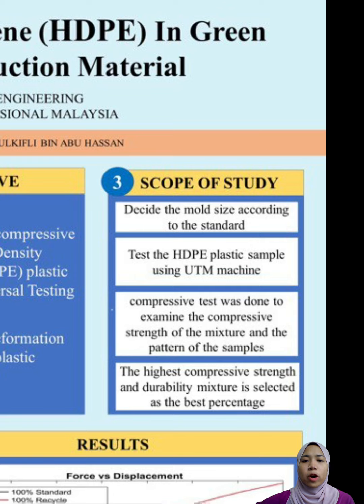Next is the scope of the study. The study of this project is to decide the size of the mold with a square shape, which is the form of testing specimen according to ASTM standard D1621, the standard test method for compressive properties of plastic. Next, the HDPE will be tested using the Universal Testing Machine. It then used the standard high-density polyethylene mixed with recycled high-density polyethylene following the determined percentage.